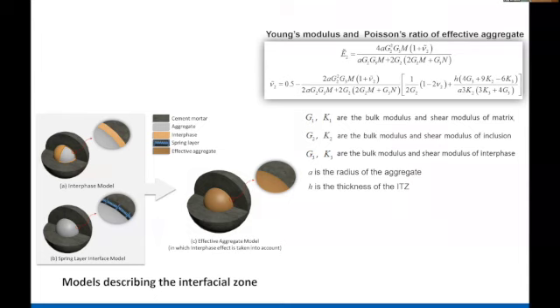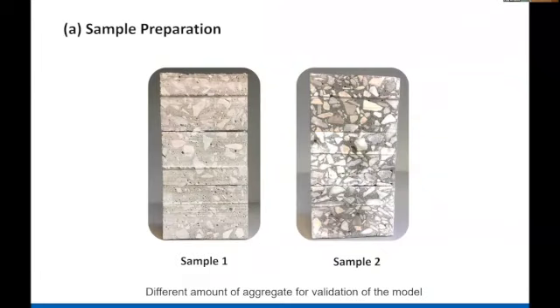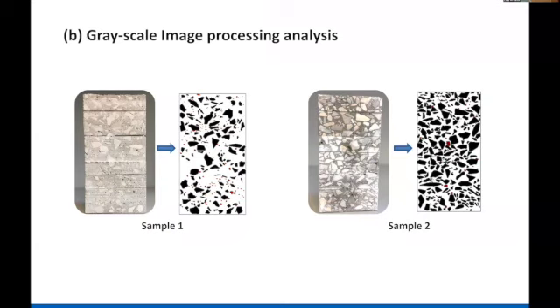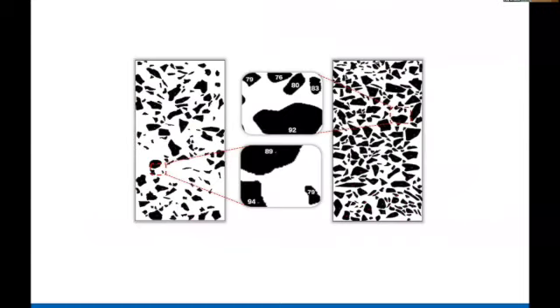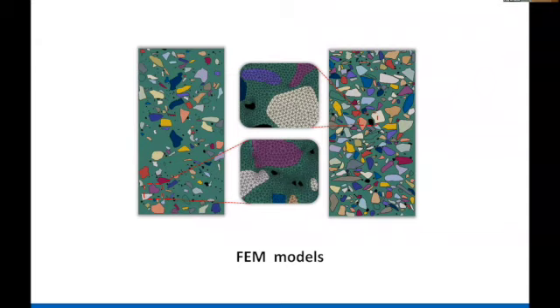Then we made two sets of concrete specimens, one with less aggregate and one with more aggregate. But that model is only good if the aggregates are spherical. So for each aggregate, by doing a grayscale analysis, we calculated the surface area equivalent sphere. So we can then calculate using the analytic model the modulus of the composite and then do the FEM to calculate the modulus. But each of the aggregates has a different modulus. So then we did FEM analysis.